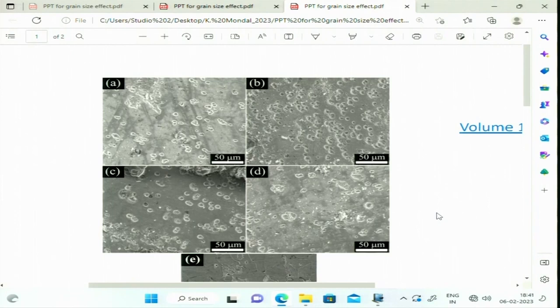And how can you change the grain size? We deform the surface, and after deformation we try to do different degrees of annealing, and that annealing led to four different structures. The as received, definitely it has a kind of uniform grain with little coarser grains, like around below 30 micron grain size.